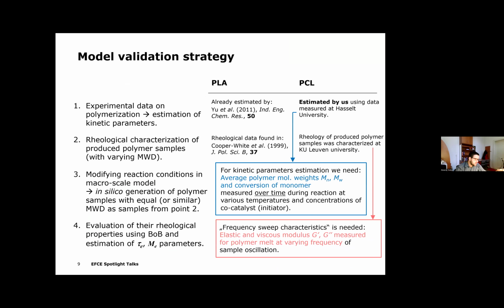So how can we validate the model or the whole framework if we have it built like this? First, we need experimental data on polymerization and also to have the kinetic parameters of the polymerization estimated. Then we need to have experimental data on rheology of the produced polymers, hopefully with different molecular structure. And then what we do is basically we modify the input reaction conditions in the macro scale model, and we virtually generate polymer samples that have similar molecular structure as the real samples. Sorry, they cannot be directly equal, but at least as similar as possible.